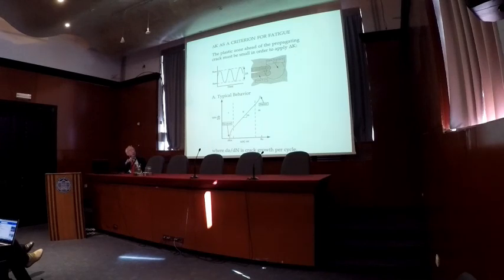You get three regions. The middle region is the one that you can do the most analysis with because you have the power law, and the bottom region here is a threshold for non-growing cracks.